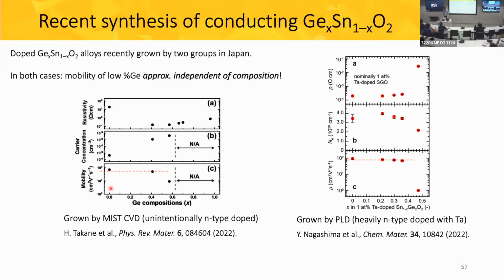One grew with mist CVD, and the other with pulsed laser deposition. So both the groups found that the materials are dopable with a concentration up to 40%. They get nice quality thin films, and they found mobilities which are high, on the order of 100, which are pretty good for devices. So here's a surprising thing. If you look at the low germanium content, what we see is that as you put germanium into tin oxide, we see the mobility remains high, despite the fact that these alloys do have alloy disorder.